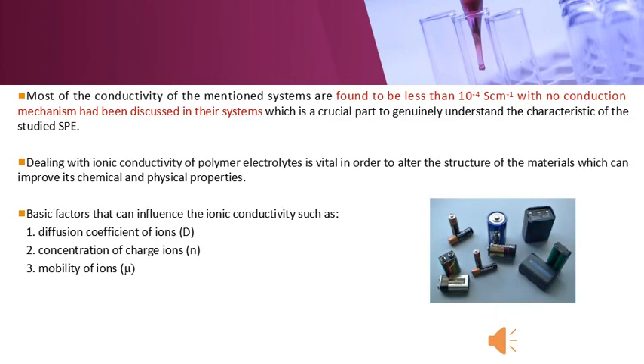Numerous works have extensively studied biodegradable, low-cost, and renewable polymer materials to prepare SPE with higher ionic conductivity and that are environmentally friendly. However, only a few studies based on such solid polymer electrolyte have been reported, where the conductivity is found to be less than 10 to the power of negative 4 Siemens, with no conduction mechanism discussed, which is a crucial part to genuinely understand the characteristics of the studied SPE.